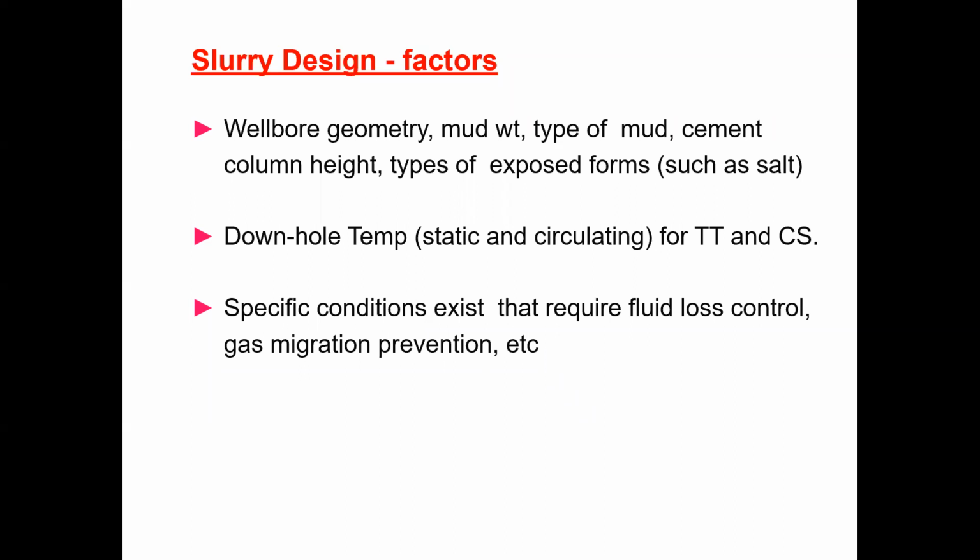API specifies how we measure it, as we do for mud systems also. We take 30 minutes at 1000 psi through a particular sieve size. For 30 minutes we collect the water or the fluid loss, and that volume is measured.